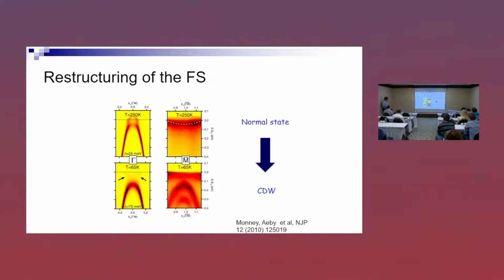Because we have restructuring, we see the same in ARPES. At high temperature in ARPES we see two pockets close to the Fermi surface: one at the gamma point, a hole-like pocket, and an electron-like pocket around the M point. Below this transition we have restructuring, and first of all we see the opening of a gap at the gamma point, and also the folding of the band coming from the M point. This is very small. So this is the evidence that we really have a charge density wave.